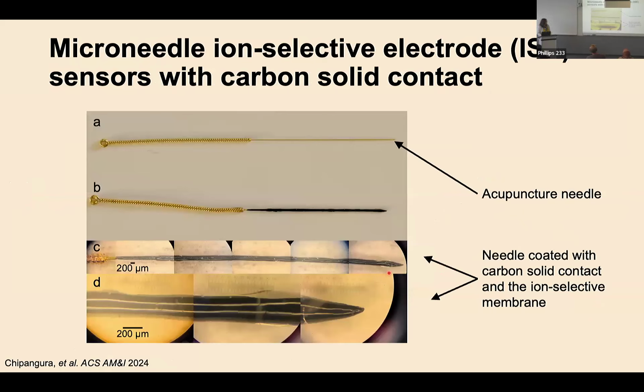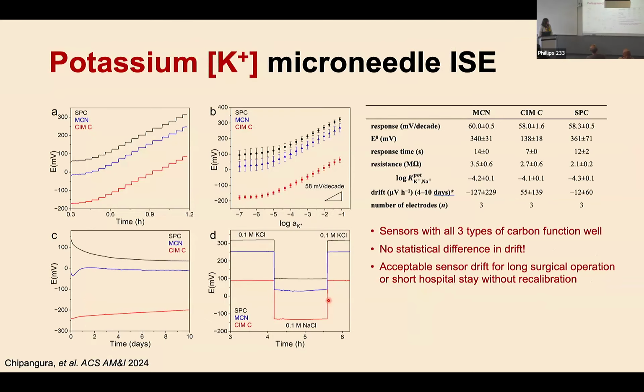This is what the first needles that we made look like. We actually used an acupuncture needle, coated that with the carbon and then with the ion sensitive membrane, and they look about like this. What we found is that we can make very highly miniaturized potassium sensitive microneedles. We were looking here at 3 different types of carbon to find out how the nanostructure of the carbon influenced the stability of the sensor. Basically, we found that all 3 of them worked.